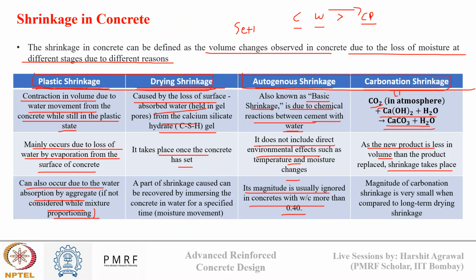So the main shrinkage problem in concrete is either before setting due to plastic shrinkage, or after setting due to drying shrinkage. That's why before setting we keep concrete properly covered inside molds so that we can avoid plastic shrinkage, and after setting we keep concrete in curing condition so that there is no loss of moisture from inside, which can cause any shrinkage issue, any delay in the hydration process, or a problem in the hydration, to avoid this drying shrinkage.